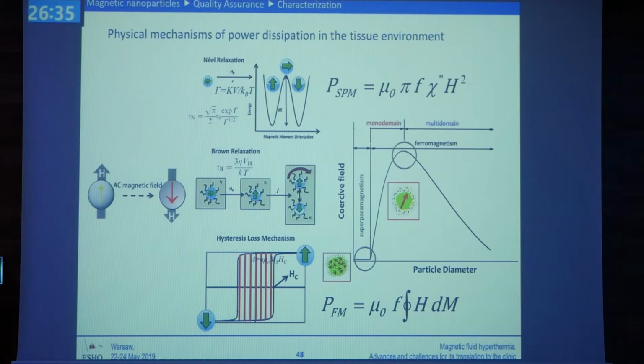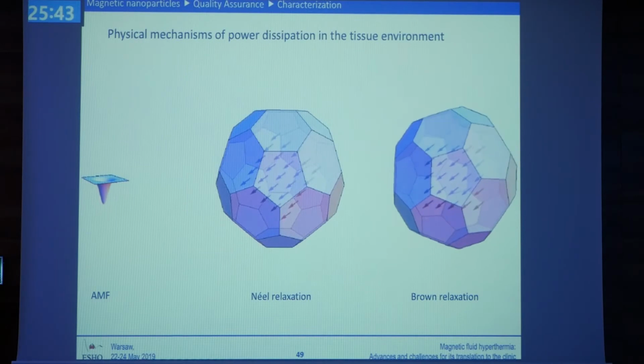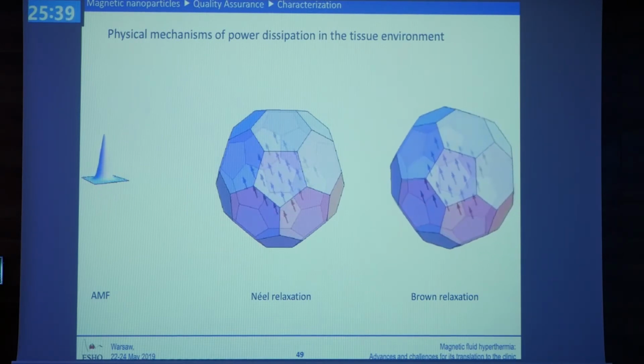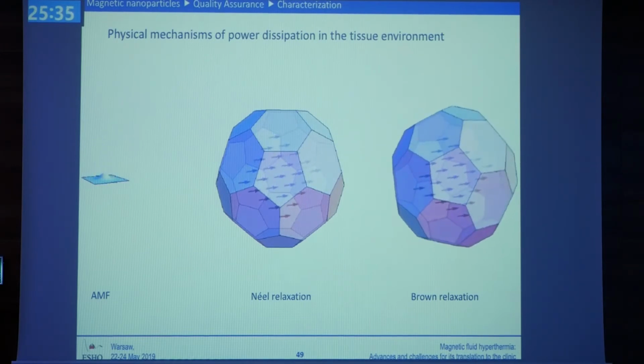Then in the ferromagnetic regime, we can have the hysteresis loop that I showed you before, and the energy that is left to the environment of the nanoparticles as the magnetic field changes direction is the area of this hysteresis loop. If the nanoparticle diameter becomes larger and larger, this hysteresis loop becomes narrower, and we cannot get much energy from the inversion of the magnetization inside the nanoparticle. So there is a nanoparticle diameter where we can get the maximum of this ferromagnetic behavior, and then we have a fall of the energy that it can give to the surrounding environment. Of course, we can also have Brownian movement. By Brownian movement, we mean that the whole nanoparticle rotates, and due to the viscous environment where it finds itself, because of friction, we can have energy release from the nanoparticle.